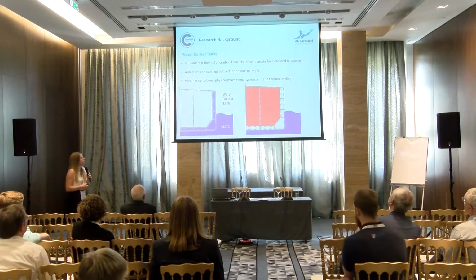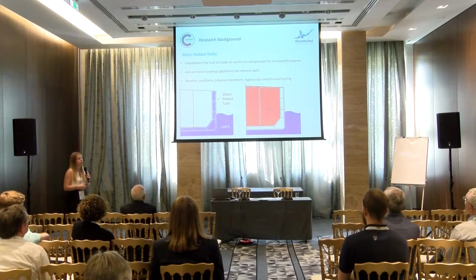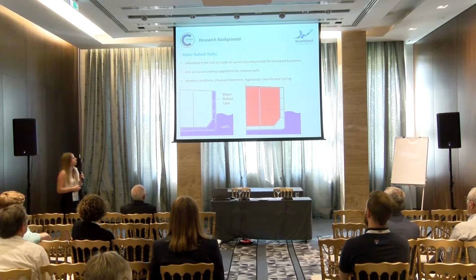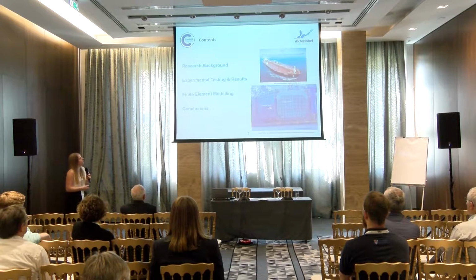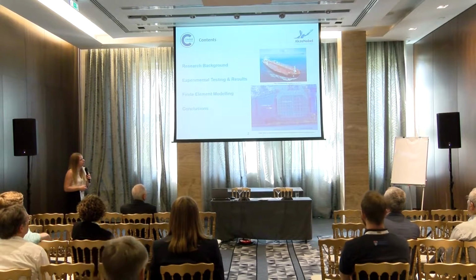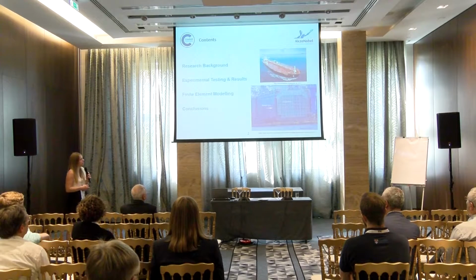However, due to the highly saline wet environment, they are particularly susceptible to corrosion failure. And as we saw in the previous image, these water ballast tanks are embedded well within the ship's hull, so any repairs are going to be very expensive and potentially dangerous, and severe corrosion can result in the scrapping of an entire tanker.